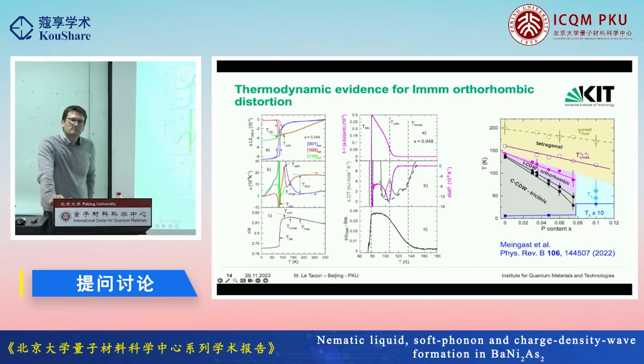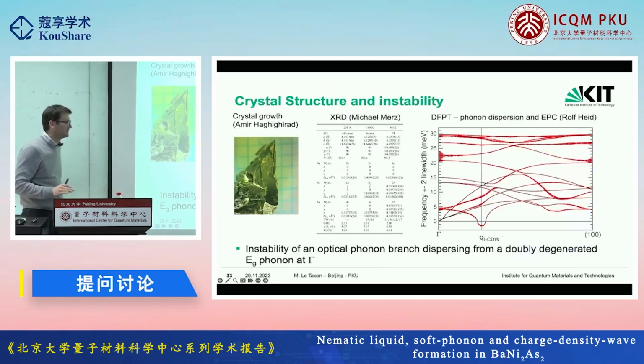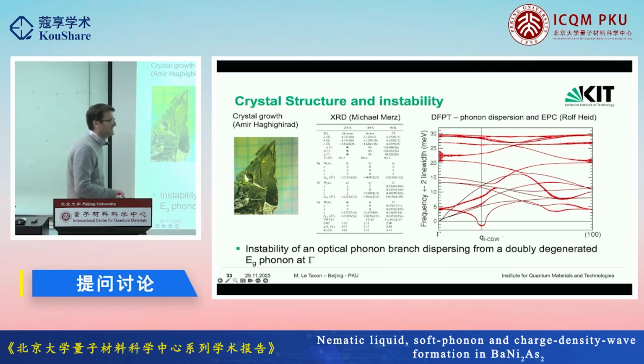I think you showed that the density functional perturbation theory calculated this phonon instability. So why do you say you still don't know the origin of this instability? Well, the density functional theory finds that the structure isn't stable. But there's nowhere in the output of the calculation something that tells you why it's unstable. That's the drama. I don't want to call this a black box, but you can put the actual lattice parameter of the structure, and find that the structure is unstable against the softening of a certain phonon. But it doesn't tell you why this phonon is so soft.